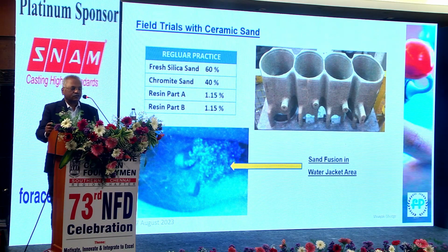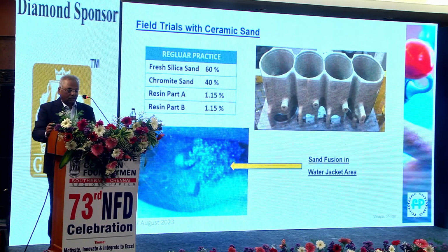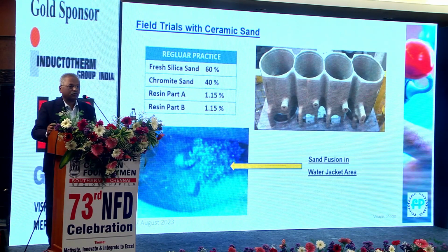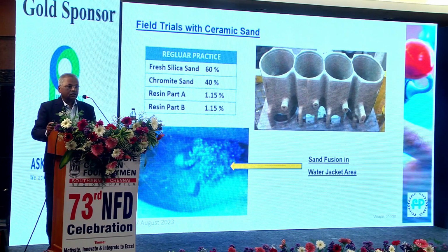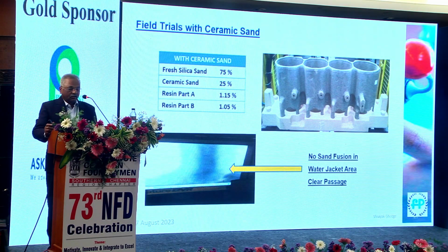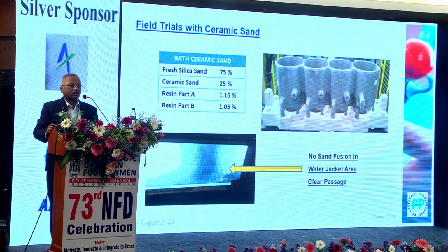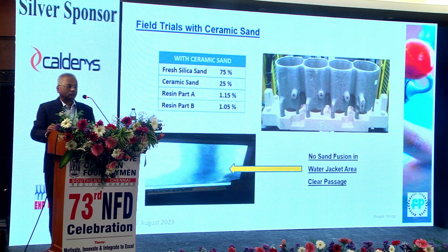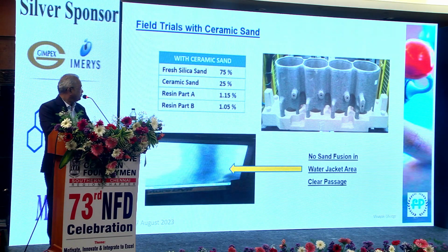These are some field trials we had taken with the ceramic sand. Earlier this water jacket core for the block was made with the chromite sand, almost 40% of chromite sand, and despite using so much chromite, they were still getting the sand fusion defect. This is a boroscope photograph which is attached. This core was made with 25% ceramic sand, and absolutely no sand fusion obtained. Clean water jacket passage.